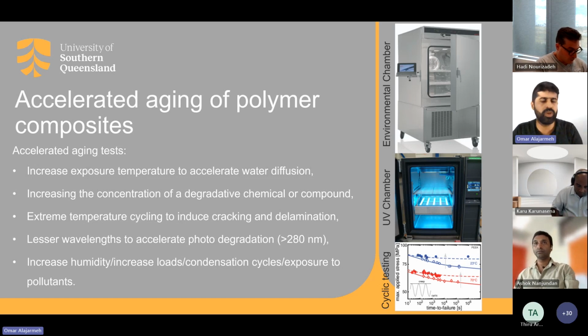And there are some points here that we use in the lab to simulate the exact environmental impact in reality. One of the tests that we are adopting is increasing the exposure temperature to accelerate the water diffusion, and this is hygrothermal. Increasing the concentration of the chemical or compound that helps in degrading the polymers is more about alkaline solutions and acid solutions. Extreme temperature cycling to induce cracking and delamination is more about freezing and thawing for environments that have high temperature and low temperature.